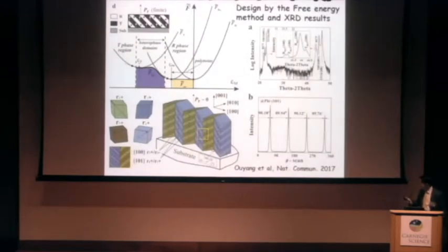Before I show you any experiment data, I just want to elaborate a little bit on my point here. You can see here, this is free energy as a function of misfit strain, right? I use the reference state as rhombohedral. You can see when there's no strain, the minimum is here. Then this green curve is tetragonal. Of course, it's higher. The ground state is higher.